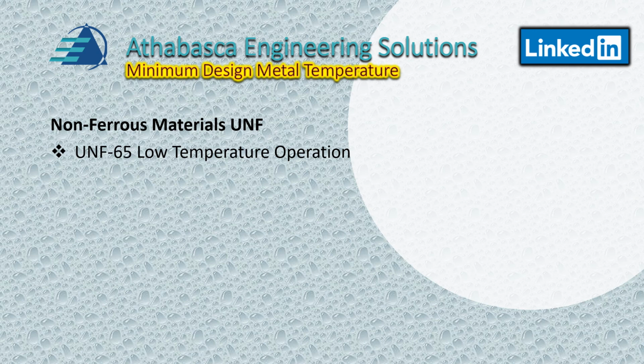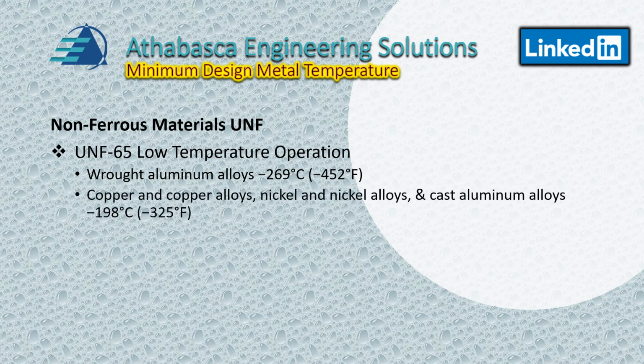So this falls under UNF 65 in Division 1. And basically this includes aluminum alloys, which is a very common cryogenic application. You're down to, basically, your minimum is minus 269. And they basically say impact tested if you get colder than that. And there's not much more to that. I think there's experience in engineering more involved with that.